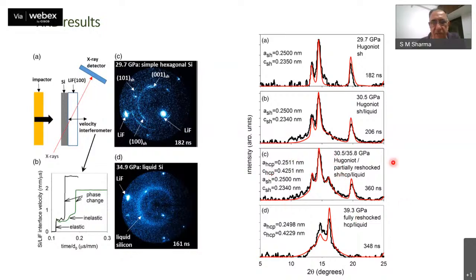And if you analyze the diffraction pattern, it is a combination of liquid phase, a small component of primitive hexagonal phase, and hexagonal close-packed phase, which was expected at much higher stresses in static pressures. And it had not been earlier observed ever in any of the shock experiments. So you can see that the reshocking took it to the molten phase and then brought it back into a crystalline phase, which was representative of the higher compressed state of silicon.